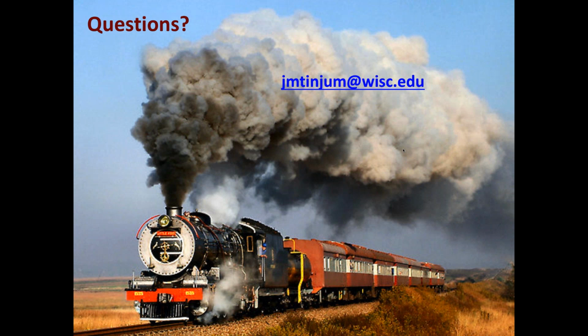But I do understand that some of my colleagues in the industry have proposed using asphalt or polyurethane stabilized layer at the bottom in rail construction to prevent piping of fines and moisture from the bottom. So a good question. The major difference is that polyurethane stabilization can occur post, not just during the construction stage, but through the lifespan of the rail.